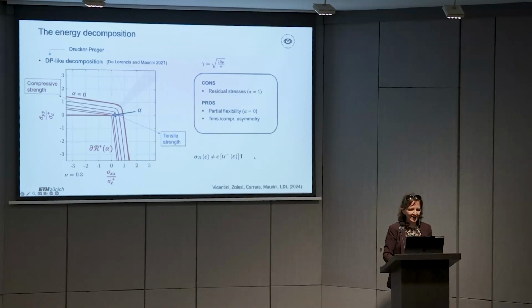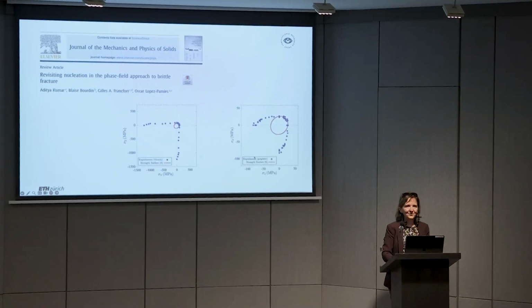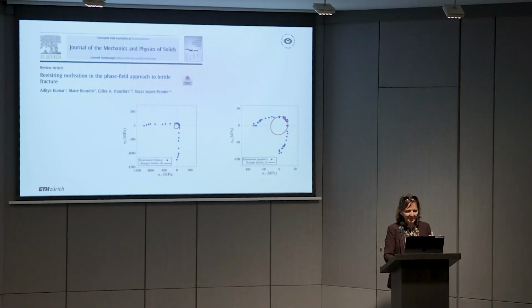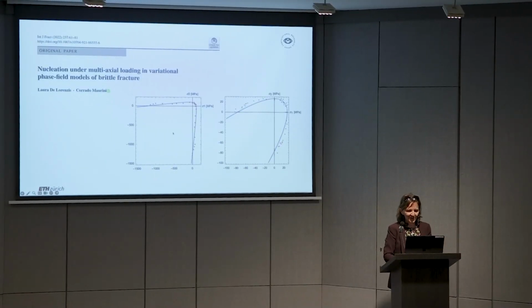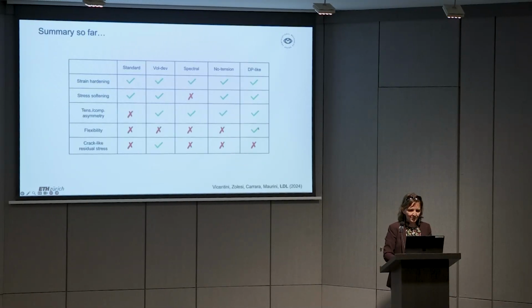So essentially we had the same issue of the sliding blocks that you saw before. But at least we could show our friends that we are able, with this new decomposition, to fit data, realistic data for the strength surface. So this was, let's say, a first step. But still not the end of the story, because now we know we tick the boxes, but still we don't tick the box of the crack-like residual stresses.